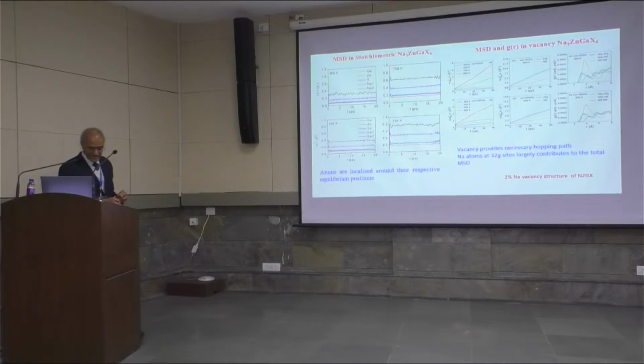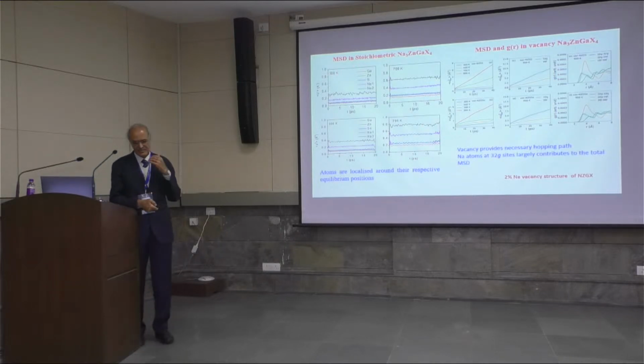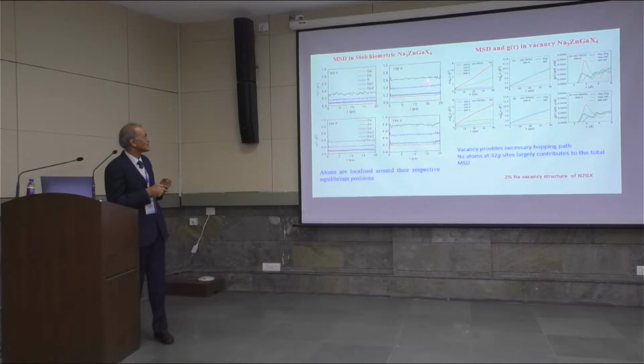Okay, so what do we see here now? Again, here you see in the real structure, the diffusion is helped by defects of various kinds. In a perfect crystalline structure, it's more difficult. So we have introduced some small vacancies, and that allows us to identify the diffusion, which you can see through how the mean square displacement increases with time. We show the diffusion. If you just look at this, you may feel it's liquid-like, but really it's not liquid-like, but strongly influenced by the underlying lattice.